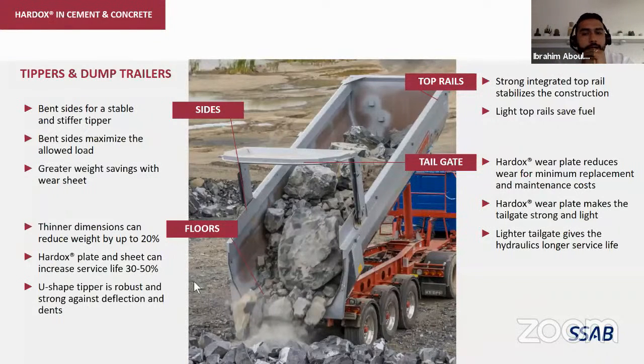Then we have the top rails, which is more or less the structure that's holding the whole tipper together. The design of these top rails has to be designed smartly in order to be able to avoid stability problems like buckling and so on. So the design has to be done in a very, very nice way. Still, also you decrease some weight in that. And finally, the tailgate, which is more or less the most part where you have damages due to when the driver is driving and the rocks are locked onto the gate, as well as when tipping, you have your hydraulics and they get a lot of damages. So having Hardox in the gate will extend the service life, as well as it will protect your hydraulics, which is very expensive for each tipper, and without it you cannot move.